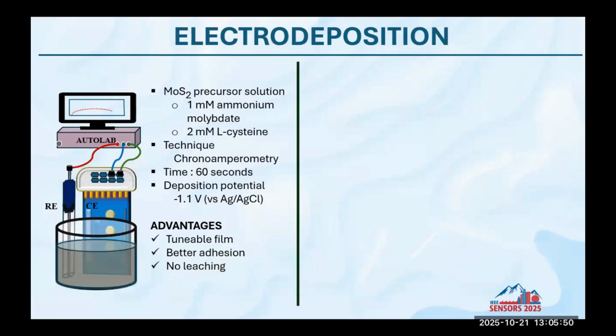And now, how do we go about electrodepositing the material on the electrode? So these electrodes are gold. The base of the electrode is gold fingers. And to electrodeposit, we are preparing a precursor solution of our material, which we want, that is MoS2. So for molybdenum, we are taking ammonium molybdate. And for sulfur, we are taking L-cysteine as the precursor.